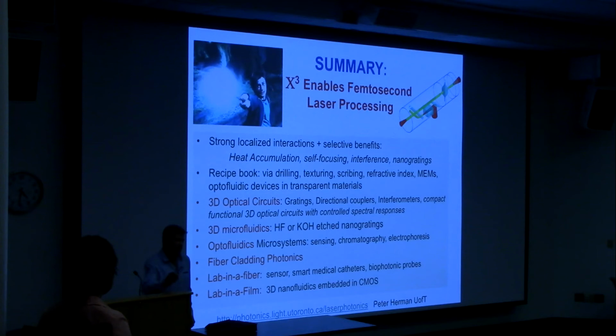But in the fiber, we're moving less than 1 millimeter per second. It's very slow. In air, we've done things up to 1 meter per second, where you need really high speed and long travel ranges because of acceleration zones. So I imagine if you go too fast, you might have bubbles and cavitation forming. I haven't thought about where the limits are, but I think we're really far away from it.